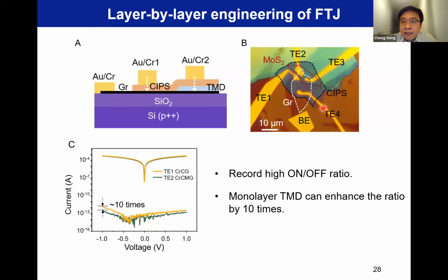As you can see in this device, you have the same substrate, of course. You have the same graphene flake and the same CIPS flake. You have the same chromium-gold electrode. The only difference is that between CIPS and graphene, the other device has one additional monolayer transition metal dichalcogenide. We tried molybdenum sulfide and also tungsten selenide. So this is a well-controlled experiment.